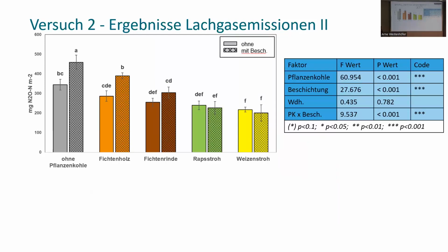If I take the accumulated results, these are the results of laughing gas emissions. Coating does have an impact, and biochar as well. And what surprised us is that coating leads to a clear increase of laughing gas emissions, particularly if I don't add biochar or spruce bark coal. When speaking about the straw-based biochars, it's inverted. The emission is lower in general, and with coating, it's also lower.